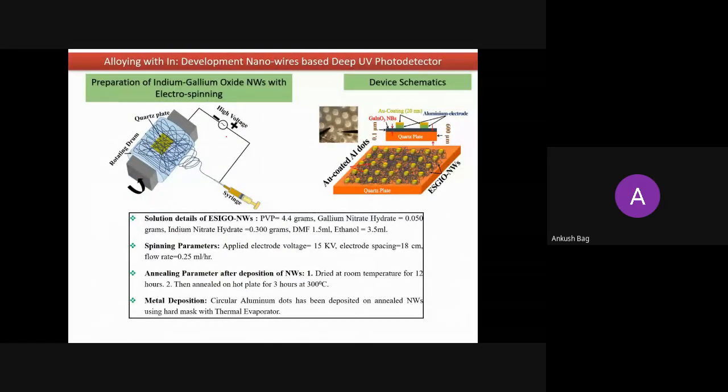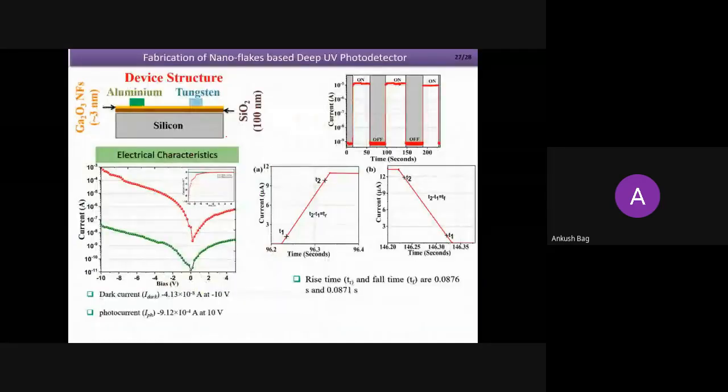So here we could achieve a dark current of 10 to the power minus 8 ampere, and this photo current, you can see this. Once again, we are getting 10 to the power 4 order of increment when we are illuminating these devices. So once again, we are getting very high performance in terms of photo to dark current ratio